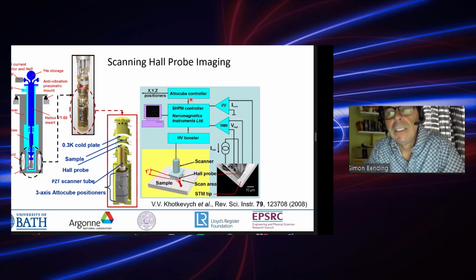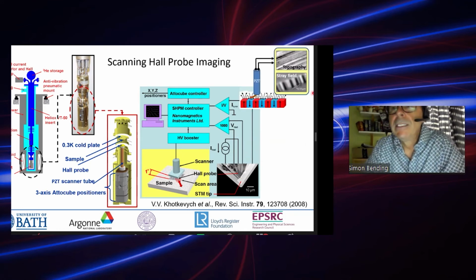So then we have low voltage and high voltage electronics, which allows us to both scan the surface of the sample and also capture information from the Hall sensor itself, also from the STM tip. In doing so, if we're in scanning tunneling mode, where we're actually tunneling into the surface and using that to track the surface, we can simultaneously correlate the surface topography and the surface stray field from the Hall sensor itself.